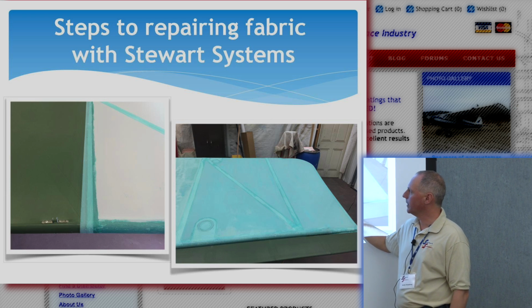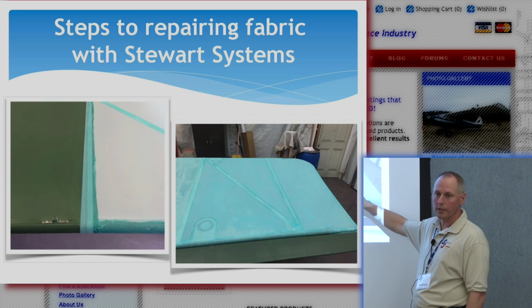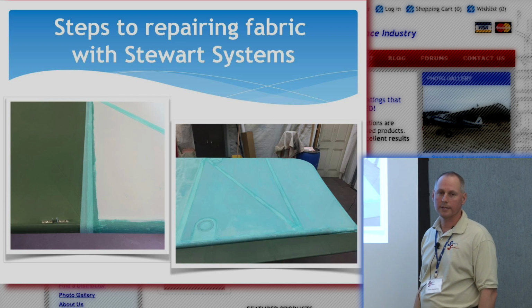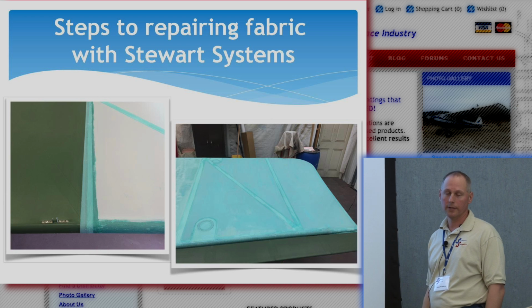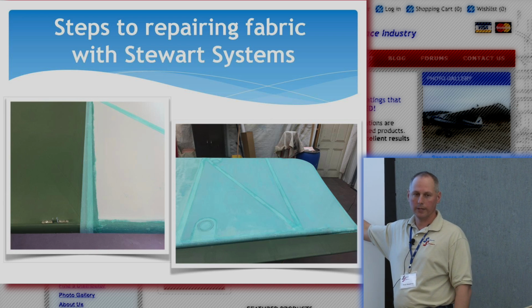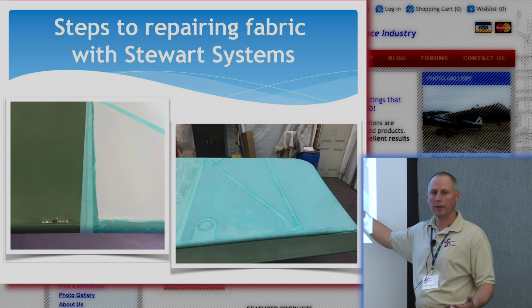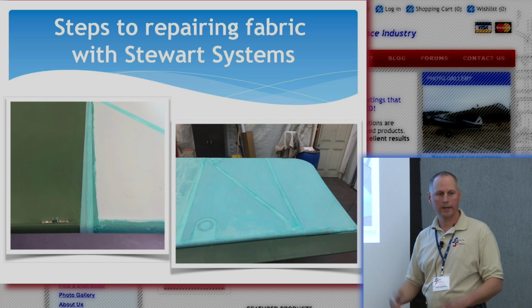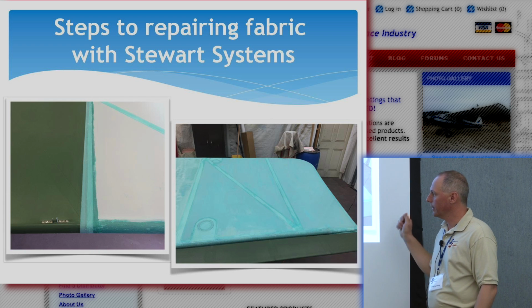The next step, we're sealing the weave right here with EcoBond. Now if you have a revision 2 manual, you're going to see sealing that weave with EcoFill. You can do it either way. We prefer to do it with EcoBond. We're diluting EcoBond 3:1, 3 parts EcoBond, 1 part water. Brush 1 coat of it in. It'll soak right in, lay down flat, dry, and you're done with sealing the weave.